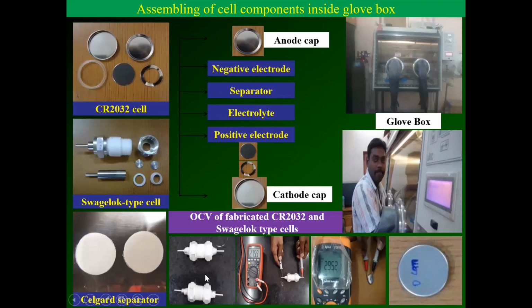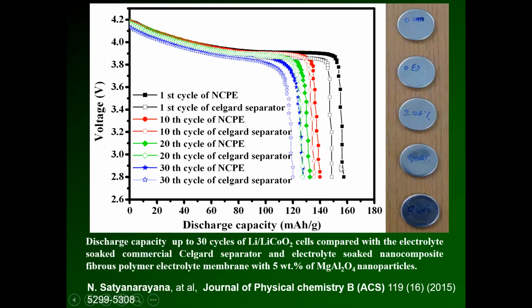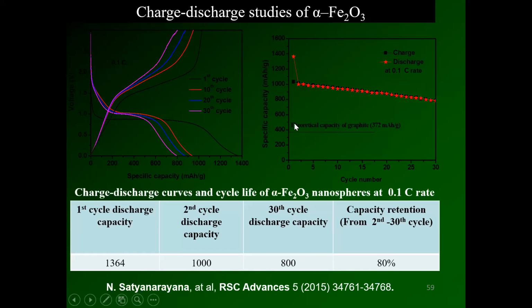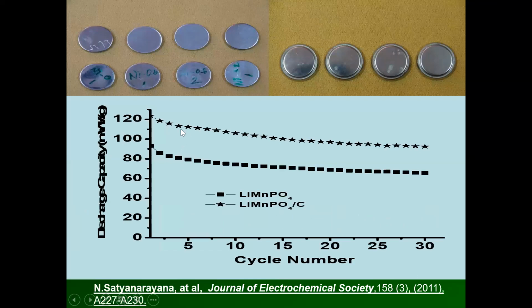Then you try to measure the open circuit voltage. Then when you do the charge-discharge characteristics, the nanocomposite polymer electrolyte developed in our laboratory by a student is showing better properties than the existing commercial ones. The same with the anode material. This is the theoretical capacity of graphite, about 400 something. Then you can see the iron oxide nanomaterial anode showing better capacity than the commercially available lithium-ion battery. Through nano coatings, we are able to improve capacity by 30 to 35%.